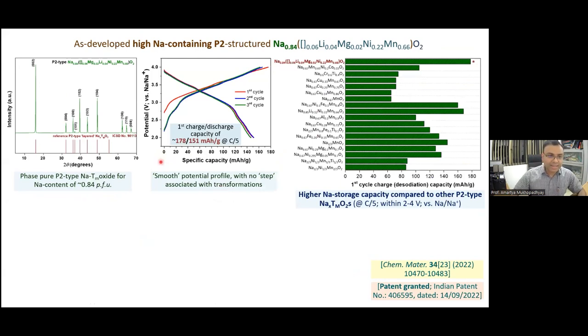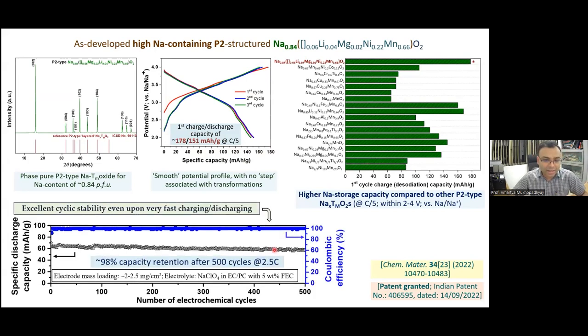And so when we synthesized it, yes, we got a phase pure P2 type structure with a fairly high sodium content of 0.84, which is fairly high compared to the typical sodium content of 0.67 to 0.7. And the charge discharge cycling within a potential window of 2 to 4 volt at C by 5 indicated that we can get a reversible capacity of around 151 milliampere hour per gram, which is better than most other P-type sodium transition metal oxide cathodes reported in the literature when cycled within the same potential window of 2 to 4 volt. In terms of cyclic stability, even at a high current density of 2.5C, the capacity hardly fades for over 500 cycles in a sodium half cell.